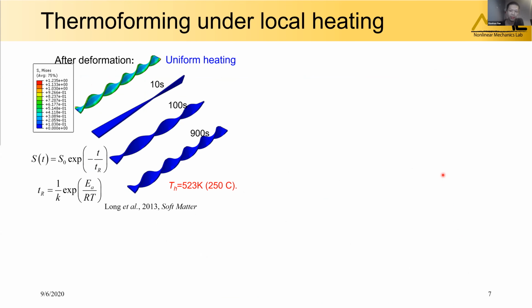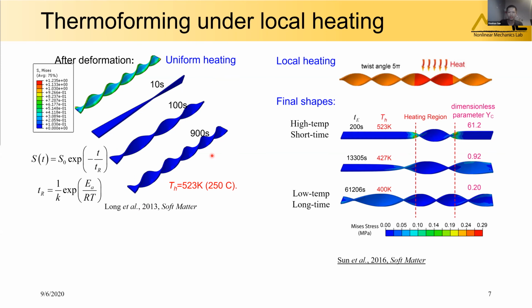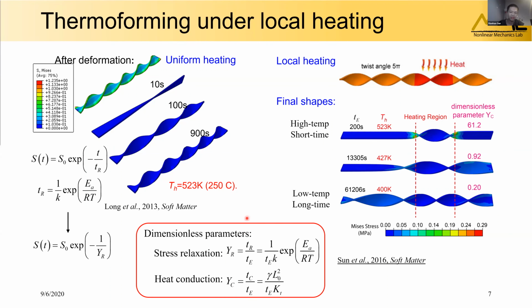So for the previous studies, first we consider the thermoforming based on the twisting. The previous study has focused on the uniform heating case. So the Vitrimer strip shows the uniformly distributed shape after the processing. If the heating is applied to a local region, the stress relaxation is coupled to the heat conduction, which can be described by the two dimensionless parameters, the YR and YC. The lower YR implies the higher stress relaxation extent, and the lower YC represents the faster heat conduction.